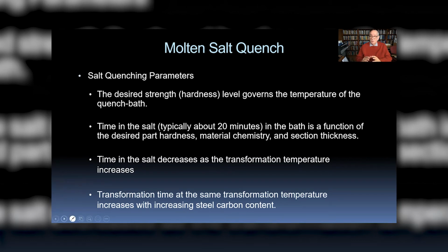Now, interestingly enough, as opposed to a part that we harden to martensite and have to retemper or temper to balance the teeter-totter, so to speak, with an Austempering process, we do not need to temper afterward, because the parts are effectively tempered, so to speak, in the salt.